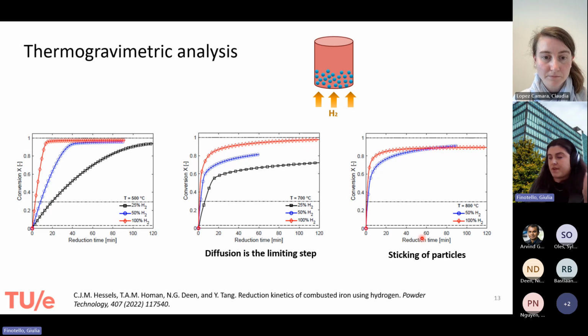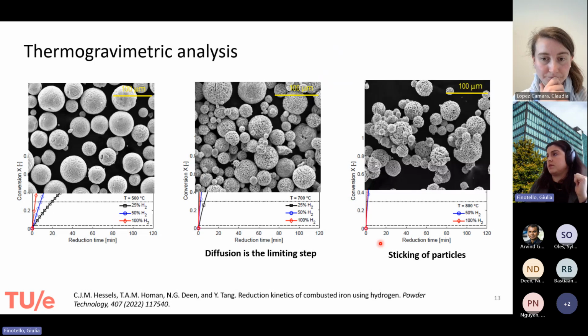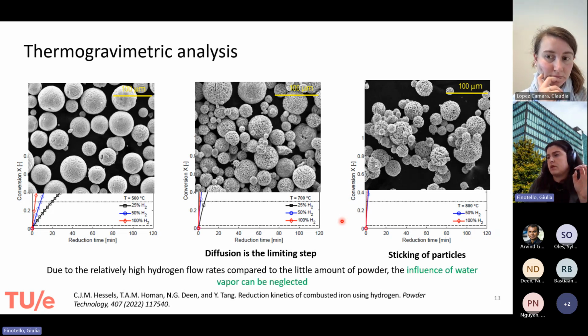Moreover, if we go to a very high temperature, at 800, we can also see sticking of particles. They start to create a solid bridge, and that's what the characterization, the SEM images, showed also, even here you can clearly see. I think that wasn't done here and was neglected, because in this case it was not important.